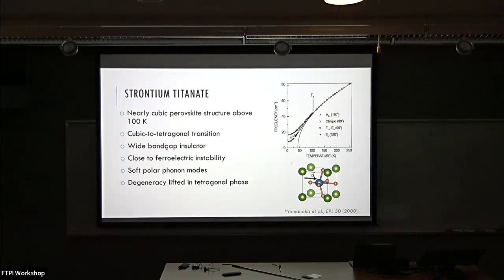Of course, as we know, this is a material that's close to a ferroelectric instability. It has this tendency for titanium to go off center. And as I mentioned, this degeneracy is lifted by the tetragonal distortion.